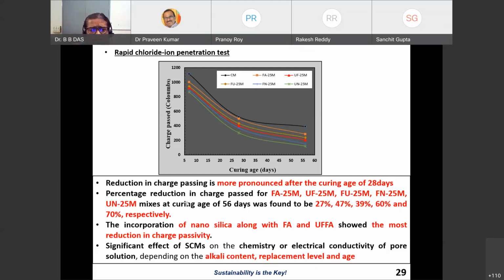Now at 56 days, the comparison is showing the percentage reduction in charge passed for fly ash, ultrafine fly ash, fly ash nanoparticles, and ultrafine fly ash nanoparticles. See how much advantage they are getting. As compared to control, the ultrafine fly ash nanoparticle mix is getting a 70% reduction in the charge passed. So that is the advantage of packing density.